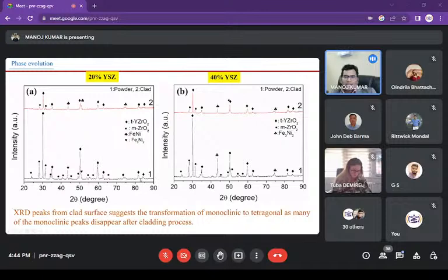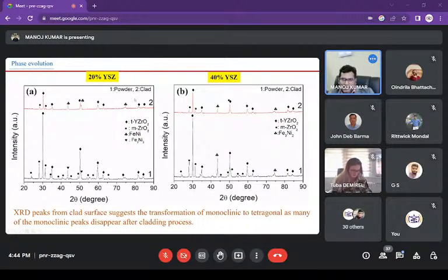So this is the XRD pattern for the mixed powder of Inconel and YSZ. So we see that the monoclinic phase of YSZ is quite prominent in the powder form, but when we do cladding, the monoclinic phase reduces, which is good. So this is another understanding of YSZ, which I can talk about on some other occasion maybe. Monoclinic is not a desired phase. We want a tetragonal phase. So why tetragonal? Because tetragonal is a stable phase, and it does not transform upon exposure to high temperature.